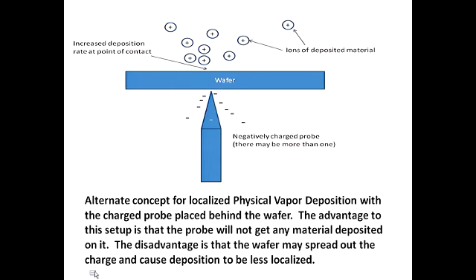Because by lift off deposition, lift off metallization, we couldn't have high aspect ratio features. The amount of deposition is limited. By this, we could have high aspect ratio. So you mean we cannot deposit thick metal and do lift off? The thickness is limited, and also the pattern. When we want to have something like that, I think this method may work. But when we use lift off and we use a layer of photoresist and then deposition, the thickness is the same everywhere.